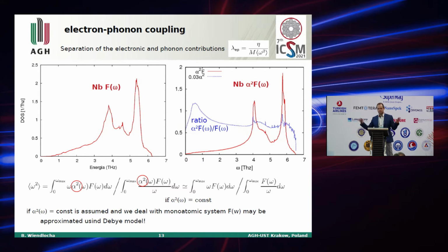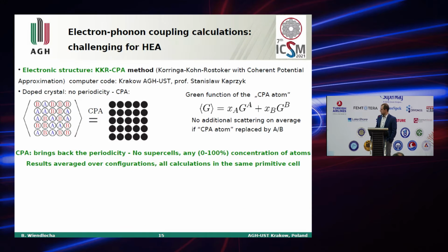So we can decouple the calculation of electron-phonon interaction into an electronic part and a phononic part after some simplifications. And the second reason I have to do this is that if we assume the alpha parameter as a constant, we can even approximate the phonon density of states curve using, for example, the Debye model. Because, as I said, this term cancels.